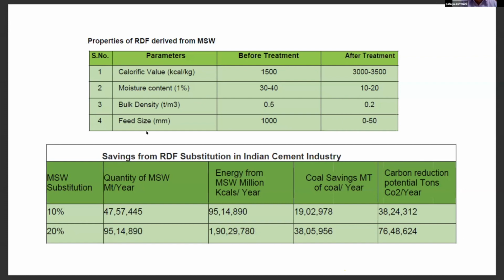And in terms of utilization, if the cement industry is able to create a thermal substitution rate of nearly 20%, it can result in utilization of about 9.5 million tons of MSW by the cement sector alone.